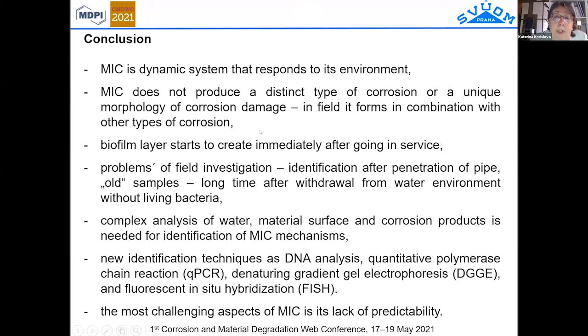in cases of such a system it is very difficult to make some prediction about this type of corrosion, because we usually solve this problem after the penetration of the pipeline, after the leakage of the system. In many cases we are not able to solve the problem immediately, and sometimes we obtain the samples of the pipe after some days or some weeks after their withdrawal from the system. So this is a problem to find some living bacteria on the surface. So we need an indirect method for the identification of whether this premature corrosion is caused by this type of corrosion. So it's one crucial problem in the industry.